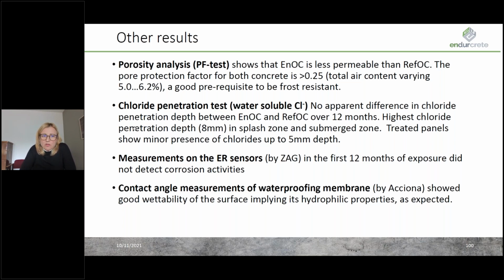The treated panels also show minor presence of chlorides up to 5 millimeter depth. The measurements using the electrical resistivity sensors performed by ZAG did not show any significant corrosion activities. And contact angle measurements of the waterproofing membrane, which was performed by Acciona, showed good wettability of the surface, implying that its hydrophilic properties are as expected.